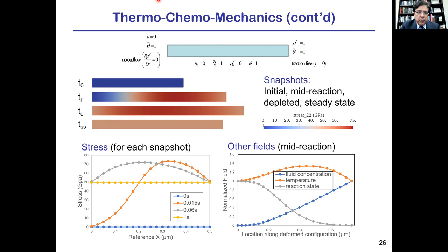So here is one problem where we have an unoriented material at time t0. Oxygen is provided at the right end. It infuses. Material is completely transformed here. Reaction is taking place here, but oxygen has not reached the other end, so it is untransformed material. Here, the entire material has transformed from unoriented to oriented material, or untransformed to transformed material, and now thermal relaxation has taken place, and so thermal shrinkage.